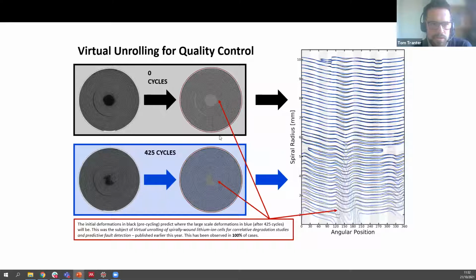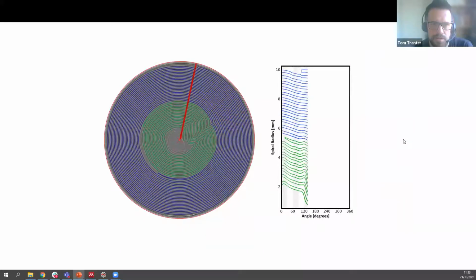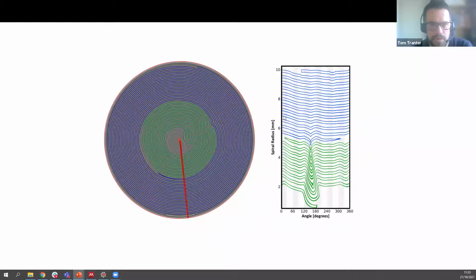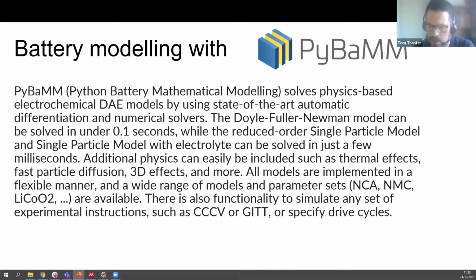With these cell level images, we can see that as you age the cells, it clearly changes over time. Certain effects make this worse or better. Sometimes a cell will have a mandrel in the center, and that will pin the electrodes into place a little bit better. But comparing the black and the blue images here, we find that you get these pinch points that propagate in the same radial position. You can see that in this nice image here over time. Well, actually, that's not over time. Sorry, that's just rolling around in the radial direction. I'll show that again.